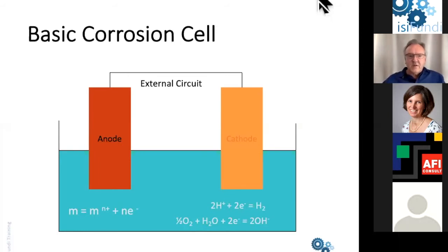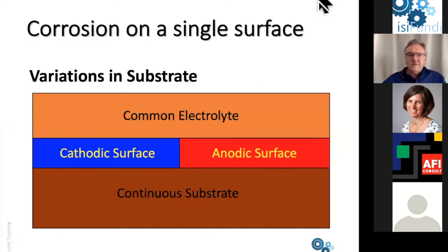Now, you may say, well, that's all very well, but on a steel pipeline, which is what we're going to consider primarily in this discussion today, we only have a single surface. The problem is that even though we have a single surface, the interaction between that surface and the electrolyte will change depending on the conditions. And so some areas of the surface will be cathodes, others will be anodes, and the underlying substrate forms the electric circuit. As long as those two surfaces are both in the same electrolyte, corrosion will occur at the anodic surface.